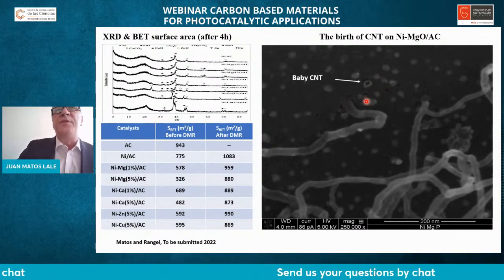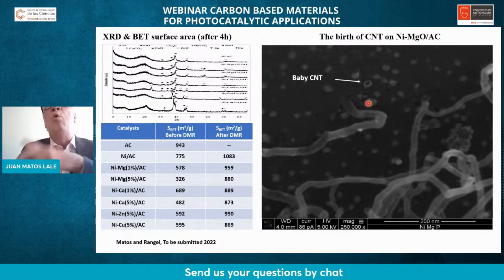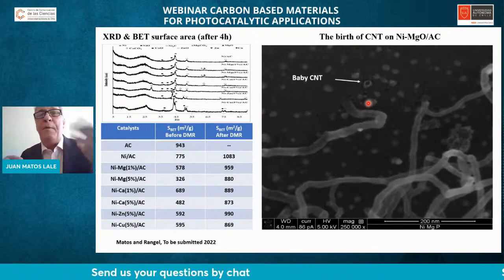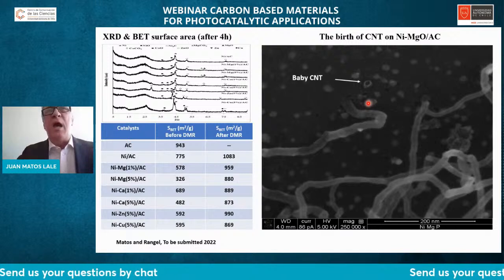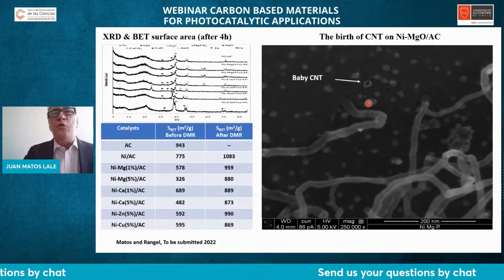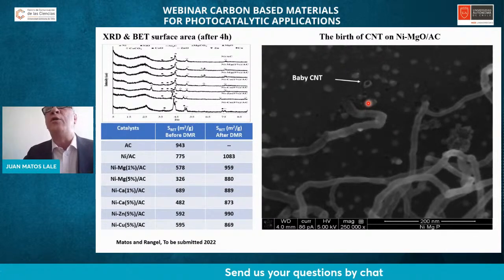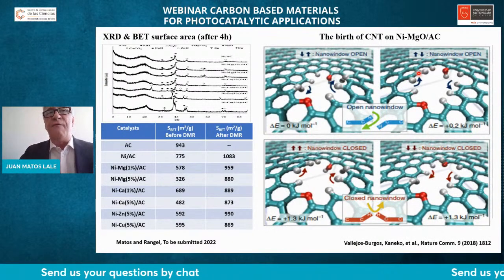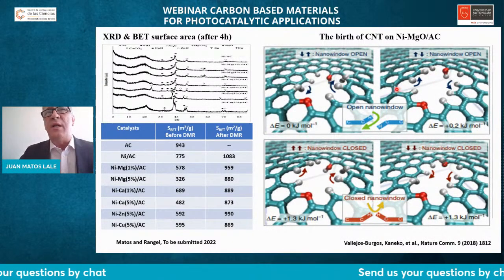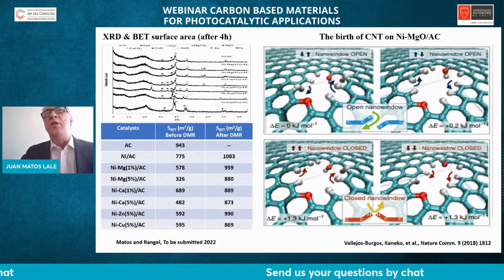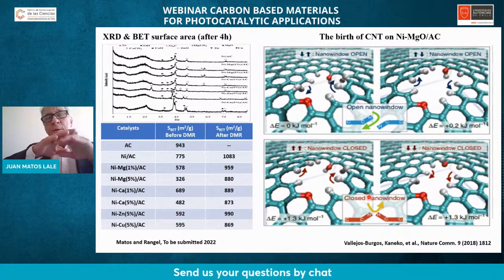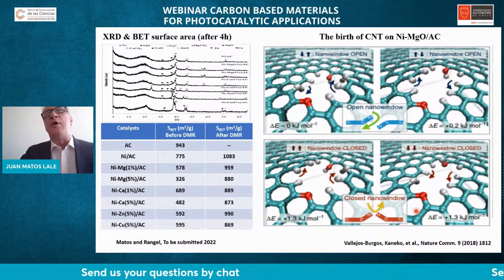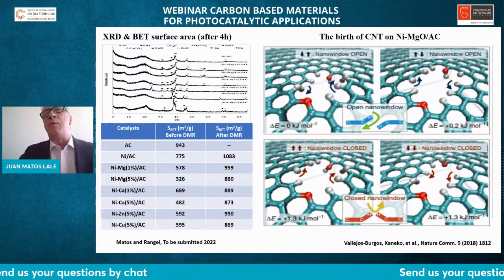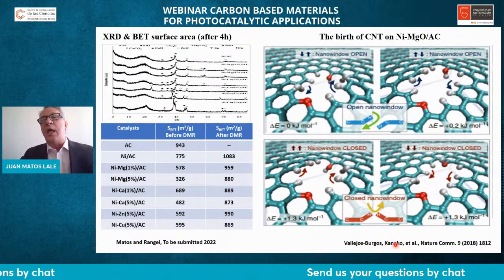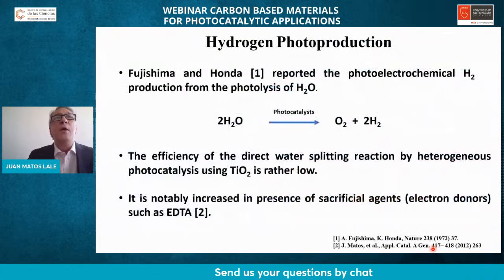We are in presence of carbon windows, and the carbon windows permit the use of nanoporous carbon as a template to produce a high quantity of carbon nanotubes. It is a very important result because it's the first experimental demonstration of the forming of windows in the layers of the graphene materials, as was reported by Vallejo Burgos and Kaneko 4 years ago. So, but